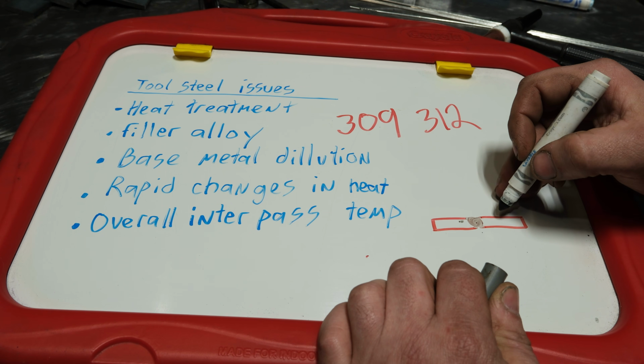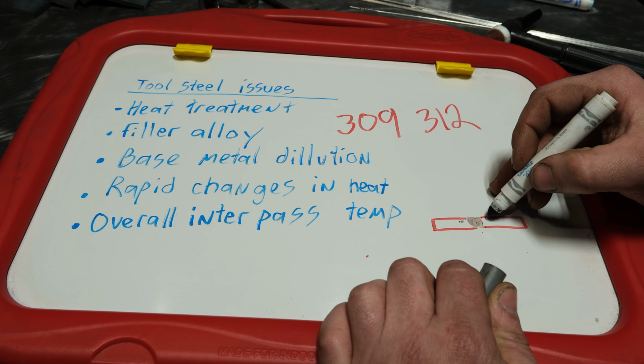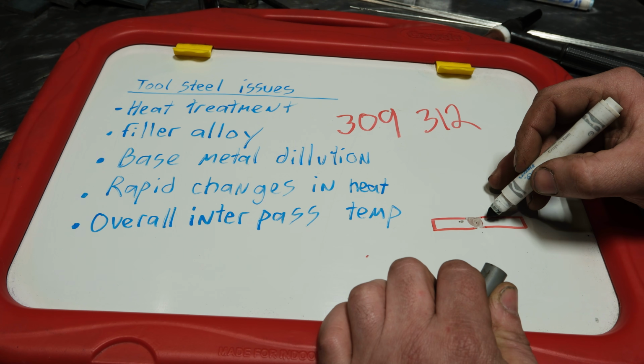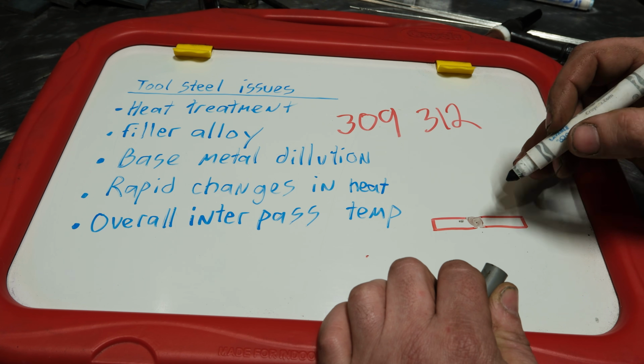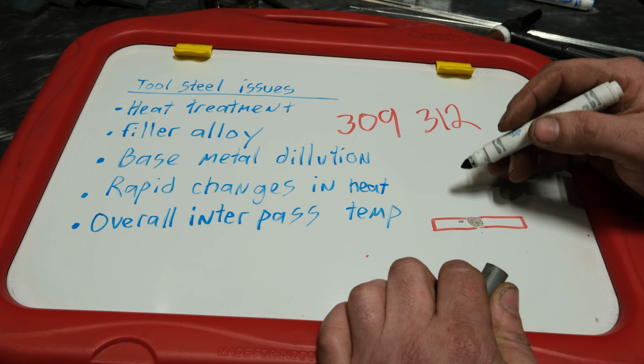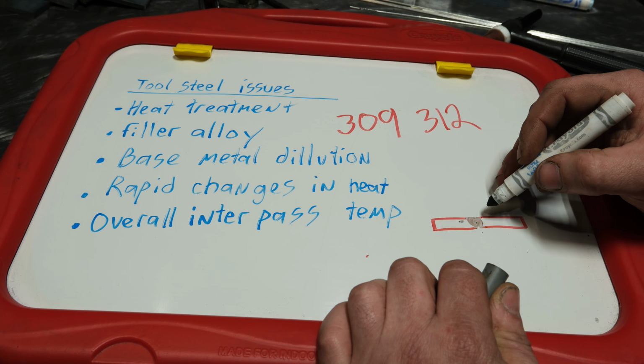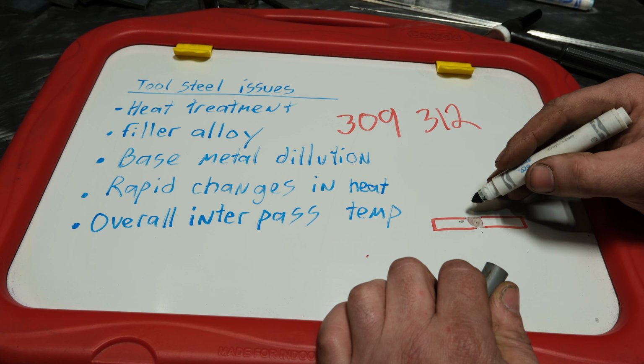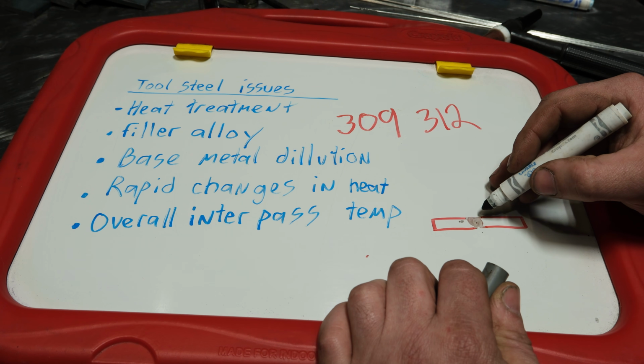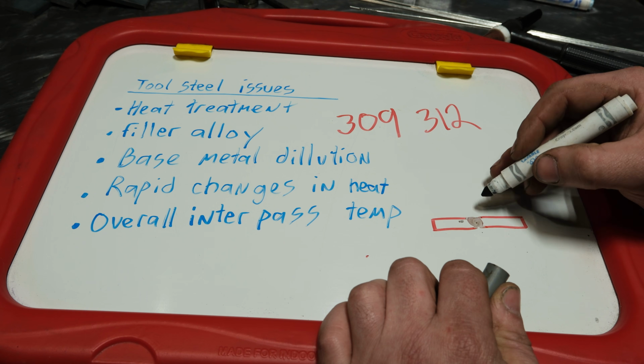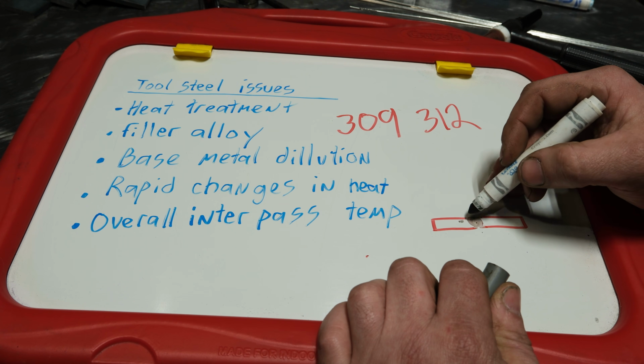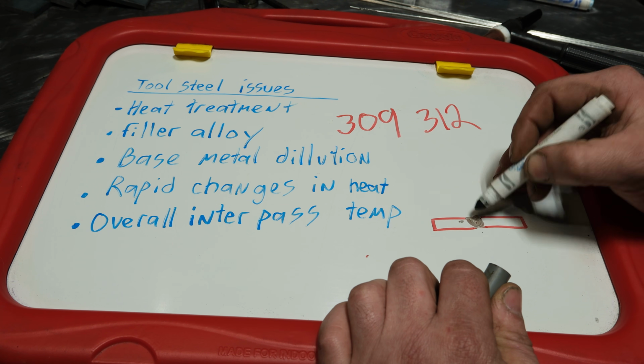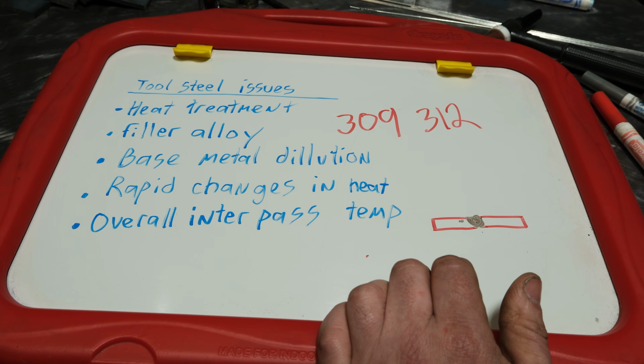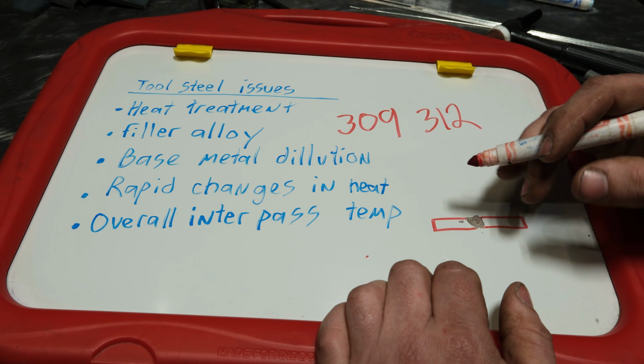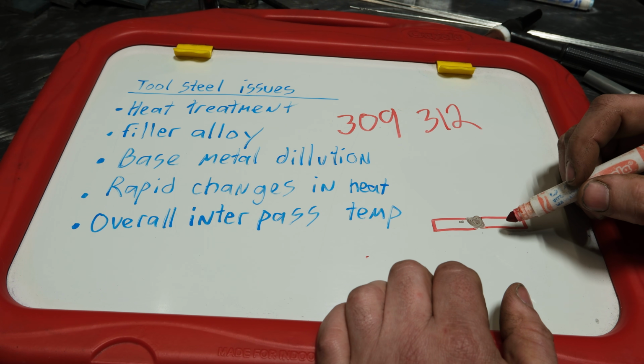And what you've got to understand is a lot of higher strength alloys do not like being welded with themselves, especially if you're not going to heat treat the finished product. So in a lot of cases, when you're welding together sockets and making your own tools, you really need to tell yourself with TIG that you must push enough filler into the molten pool so that you do not just wind up melting both pieces of base material together without enough alloy in it, because you will produce brittle welds or welds that don't perform the way that you would expect.